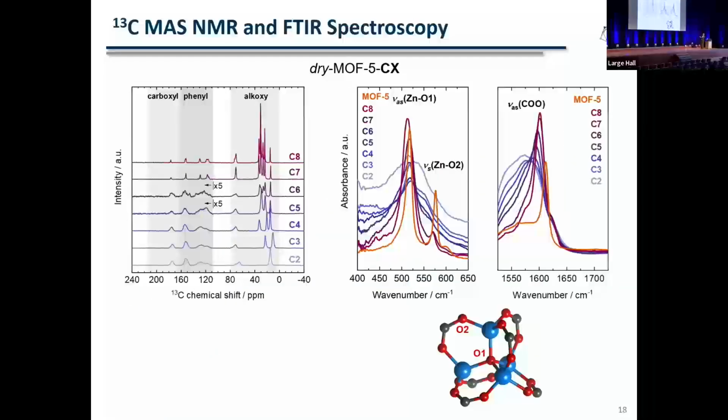All right, so this is then in agreement with IR data, we see that the symmetric stretching vibration, representative for this tetrahedron, gets very broad, and the asymmetric stretching vibration of the carboxylate also gets very broad. So that means we have different configurations. We have a distortion. Importantly, what we see in NMR spectroscopy is we do not see a free carboxylate.